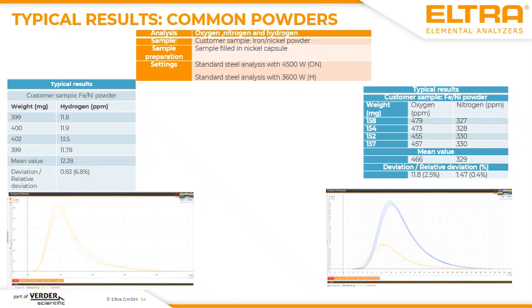It was the same for hydrogen. There we applied even higher sample weights of approximately 400 milligrams, and here we also get repeatable results for hydrogen. In such cases, the only difference between, I would say, a standard analysis of steel and of solid sample and